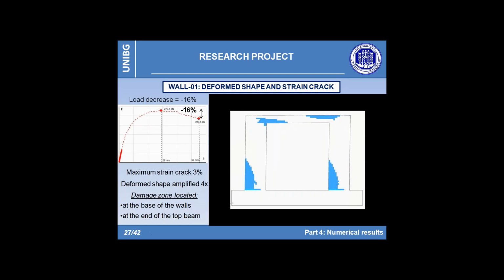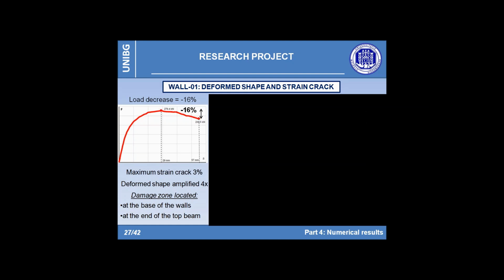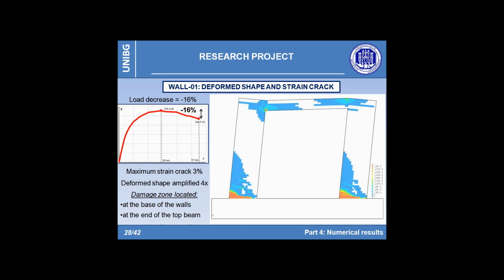In this video, the deformed shape assumed by the specimen with the increase of the applied displacement is shown. The deformed shape is amplified 4 times, and the crack strains that occur on the structure are presented. The crack pattern observed for wall 1 is highly symmetric, with ample cracking zones which affect the bases of both structural walls, and with the formation of plastic hinges at the ends of the top beam. In this way, once the structure reaches its ultimate bearing capacity, it can be noted that the top beam is able to guarantee a coupling action between the walls.